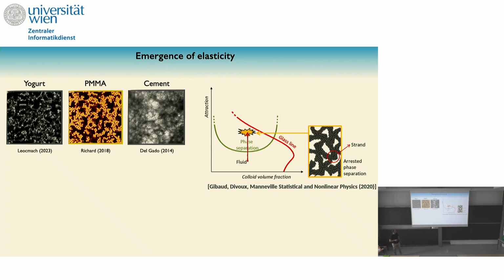But when you put the particles together and they start to aggregate, the kinetics of the aggregation process is very important. If you start from a fluid suspension and the system starts to aggregate, you enter this regime, and then the system starts to form strands that are connected together to form a network. Then the kinetics slow down and the system gets stuck in an arrested state that I would call a gel, where you have strands connected together forming a percolating network. So this is a textbook vision of how this system forms.